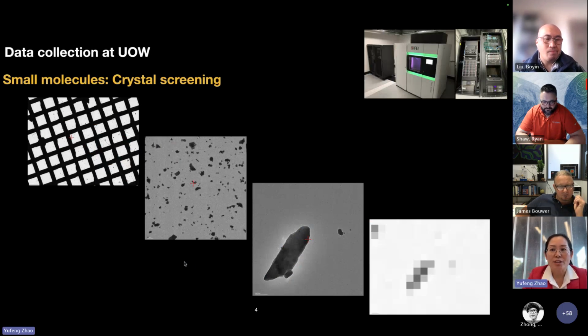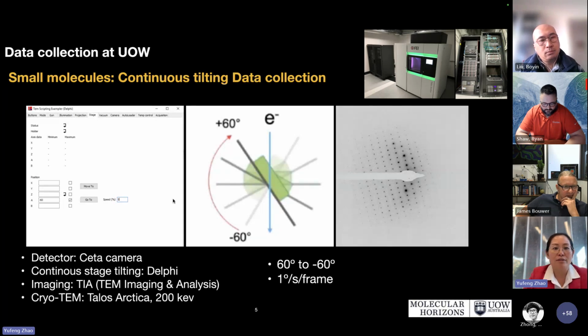For data collection, we are a little bit different because we use all the regular equipment. We use a Talos Arctica microscope. Here's where we store the data, part of our supercomputer system. After the crystal screening, for data collection we also use the continuous tilting scheme. It's just we don't have the automated collection software, so we do all manual work. And all the hardware is normal, like the detector, we just have a normal Ceta camera. Most MicroED teams use the Ceta-D camera for diffraction purposes.